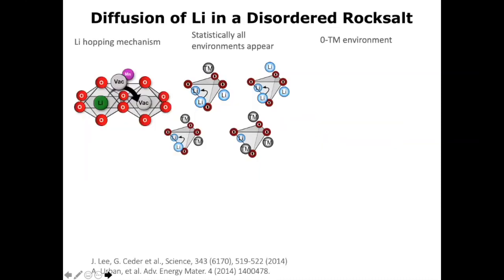And Clare gave a wonderful introduction already to how diffusion occurs in disordered rock salts or in any rock salt geometry in general. Again, rock salts are FCC anion packed. The cations are usually octahedral. So the way you diffuse from one octahedron to the other is through the face-sharing tetrahedral site.